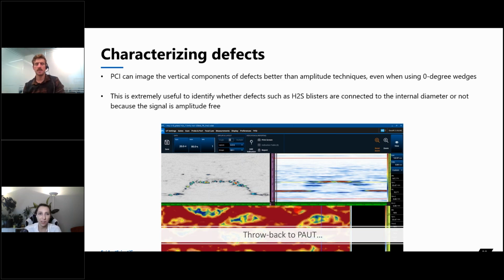Yeah, and so something else about characterizing defects is that, obviously when we have 0 degree, we can do something that is parallel to the surface pretty easily, but what's vertical is very important too. So here we're showing some H2S blisters, where what's important with this type of damage mechanism, also known as stepwise cracking, is to know if something is connected. Is this connected to the ID or to the next blister? If we can see a connection, it's much more important for the asset owner to know, because it can zip open pretty easily at this point.